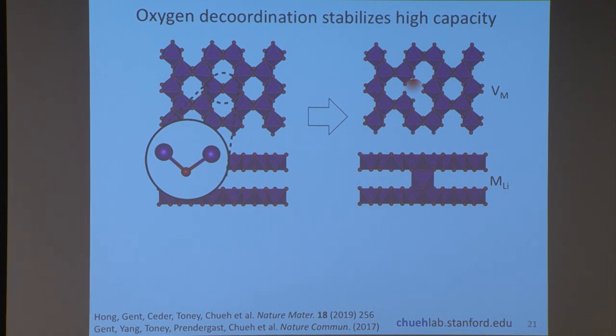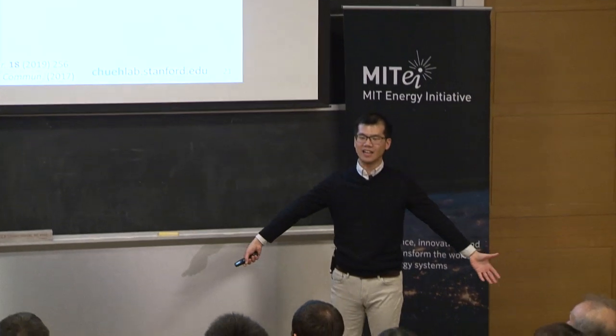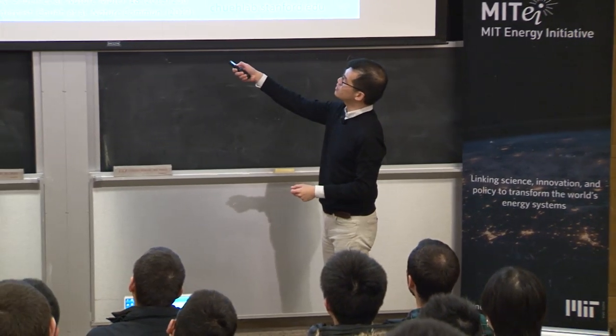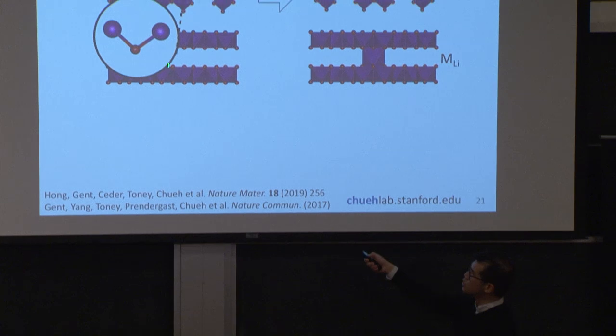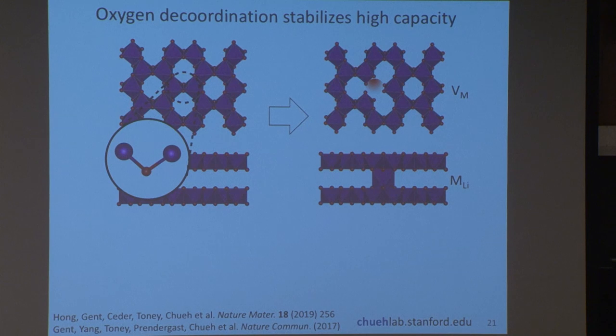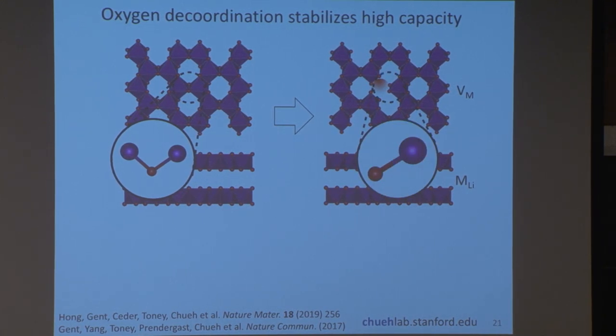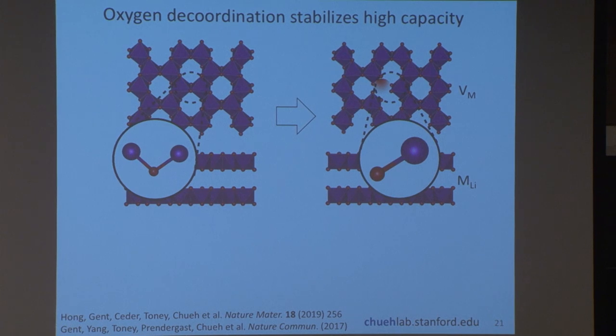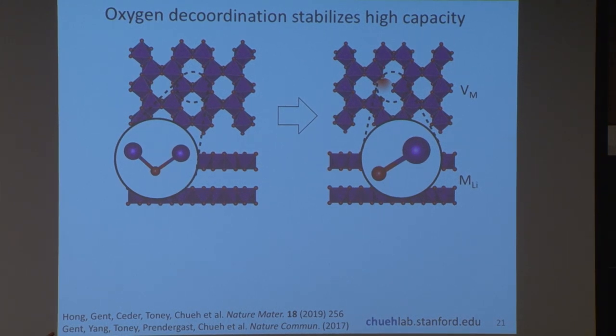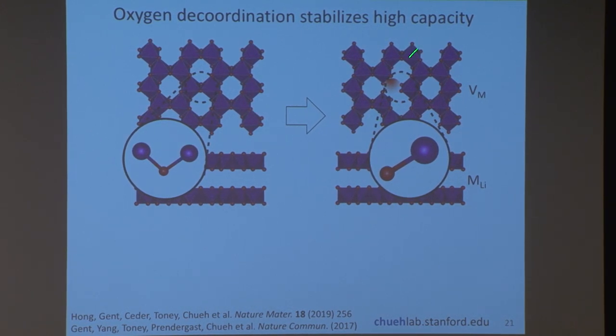On the left, the bonding between the metal and the oxygen, with the oxygen in the center, is doubly coordinated. If you have taken coordination chemistry before, you know we typically put metal in the middle and we look at the ligands, which are the oxygen. But here you actually see the center is oxygen. This is before the metal moves out of the way. And this is what happens after the metal moves out of the way. The metal vacancy is formed. The oxygen dangles, right? Because no longer do you have a metal atom there.